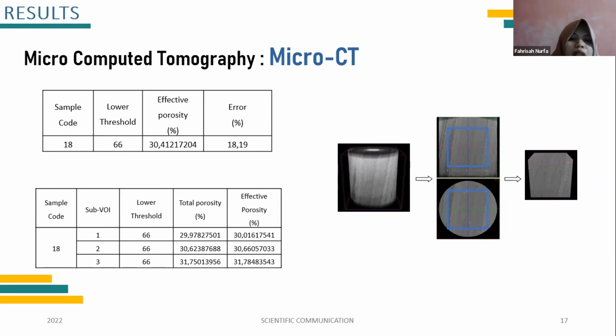One of the most influential processes in CT Analyzer software is the selection of the threshold value. We choose the threshold value because at the threshold adjustment, the sample portion will be divided into solids and pores before being converted into a binary image. The effective porosity we get is 30.412% with an error of 18.19%.